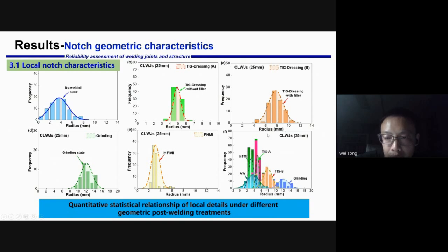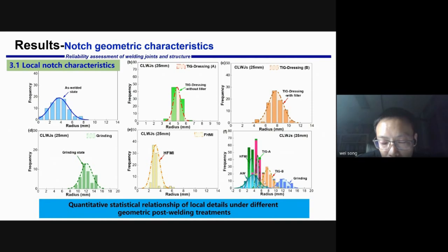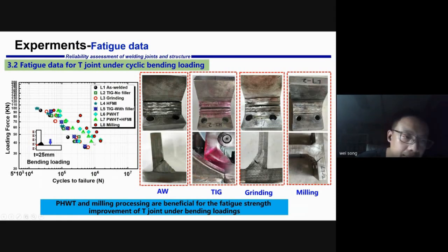As in the last pictures, we can see that the radius of the weld toe is largest for the grinding post-treatment, and the as-welded joint owns the lowest notch radius. So we can get the fatigue test result. We can see that the as-welded is the lowest point under different stress amplitudes. And we can find that the PWHT and the milling processing are beneficial for the fatigue strength improvement for T joint under bending loading.